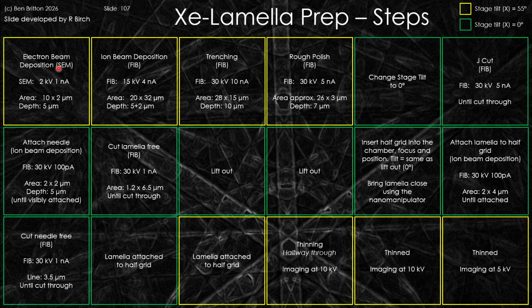So we start off with a protection of the initial cap layer with an electron beam deposition. This whole lift out was produced on a xenon FIB in this particular example. And so here we effectively now put the electron beam deposition. We're going to do an ion beam deposition. We're then going to trench. We're going to roughly polish to give us the thin lamella. We're then going to do the undercut, the J cuts in here. And then we go through the process, and effectively we're now going to have it that we've undercut.